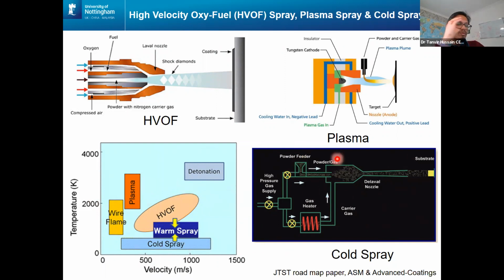So cold spray was first invented in the 1990s in Russia. And at the time, people were experimenting with particles in a supersonic wind tunnel. And what they noticed is if the particles travel fast enough, instead of eroding the surface, they actually deform and stick to each other and form a coating. And so the industry has developed quite significantly.